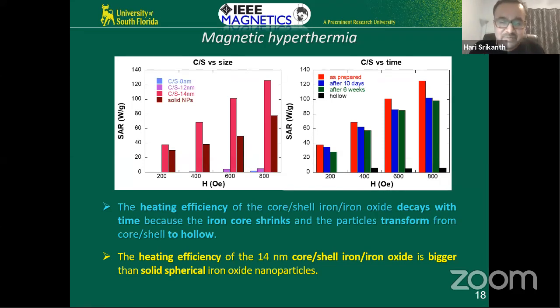However, we were excited because we thought that the hybrid, having a core and a shell and having two magnetic materials with an interface, is the best way to go. Except that we should avoid the Kirkendall effect, and we should try to look for all-oxide core shell hybrid particles where this problem of metal ions and oxygen ions diffusing at different rates does not happen.